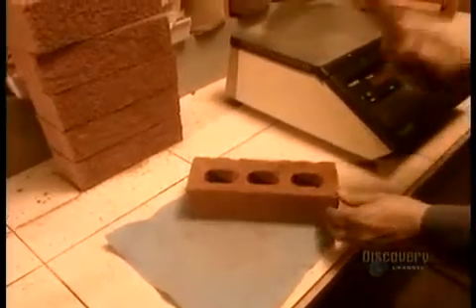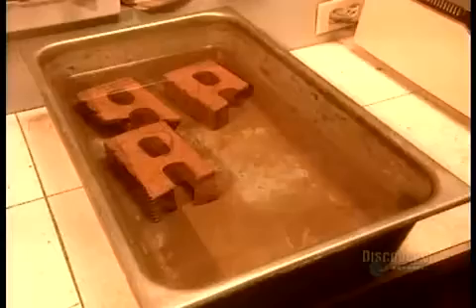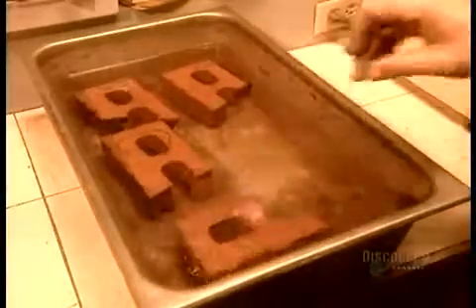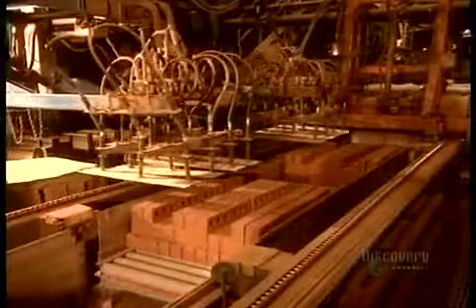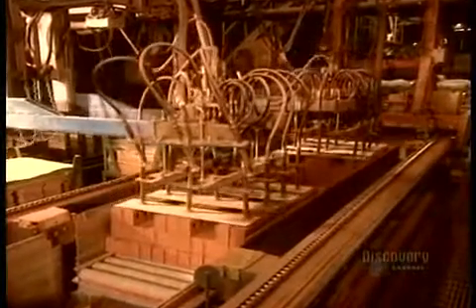So to test absorbency, the technician breaks a brick in half. He weighs it before and after soaking it in water for 24 hours. By comparing the weights, he can see how much water the brick has absorbed. Once the batch gets the okay, they stack the bricks into cubes of 500 to 600.